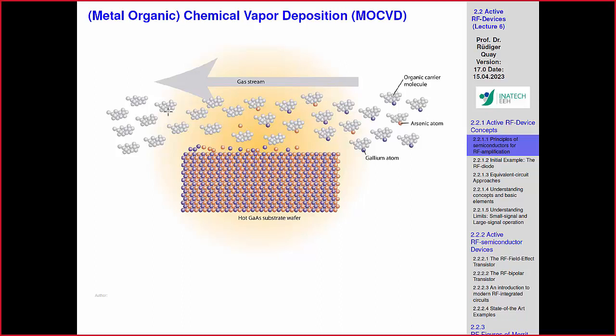And you have a relatively significant material incursion. You're growing atom by atom, but if you put enough gas and do this the right way, then it's a very steady growth. What is also important is that this is a perfectly laminar flow of the gas, so there's no turbulence at all in this. This thing is running at 500 to 1000 degrees, but you have an absolute laminar flow over the surface. So this is the trick. And then you remove all these organic molecules, so to say, and you keep the material. And then you have a more or less perfect crystal.